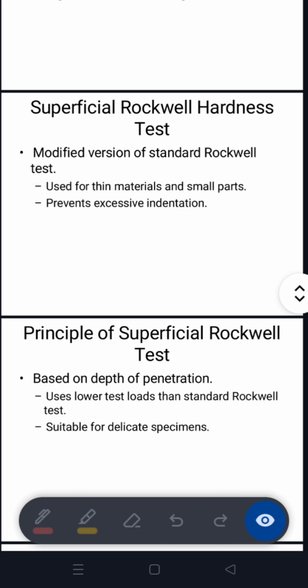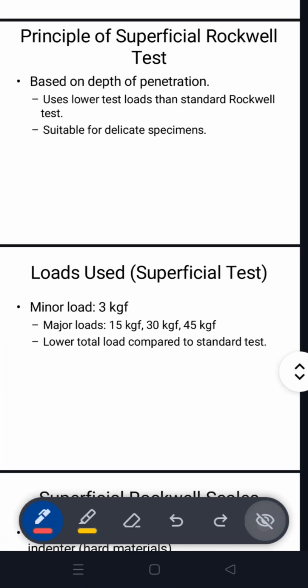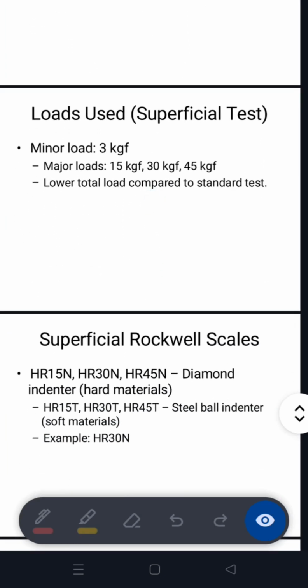So, in superficial testing, the minor load is 3 kgf and the major loads are 15, 30 and 45 kgf. Because the load is smaller, the indentation is shallow. The total load is lower compared to the standard Rockwell test. This test is especially useful for thin metal sheets, case-hardened surfaces, small precision parts and coated materials. For example, if a component has a thin hardened surface, the standard Rockwell test may penetrate beyond the hardened layer and give a wrong reading. But superficial hardness testing measures only the surface layer hardness accurately.